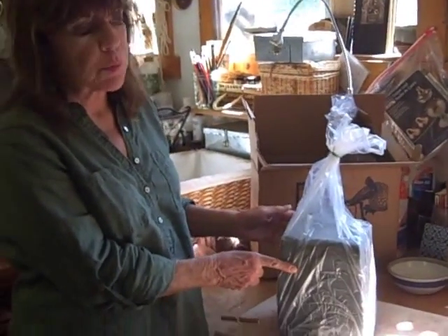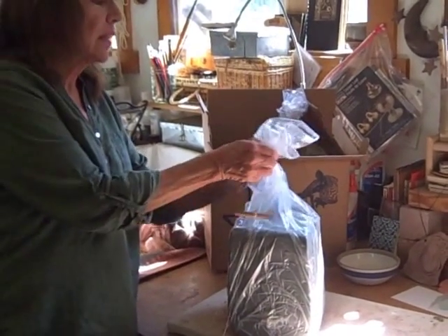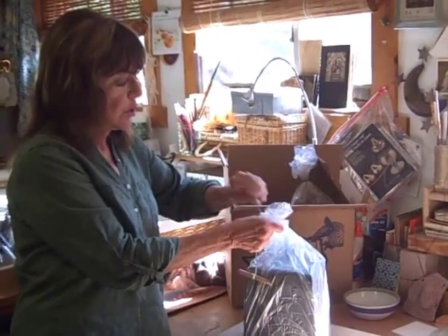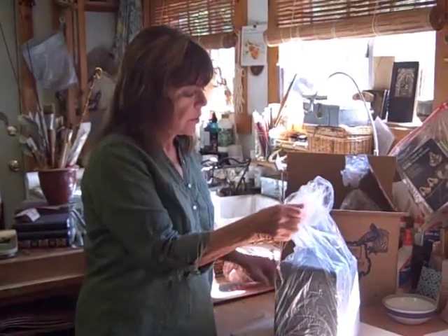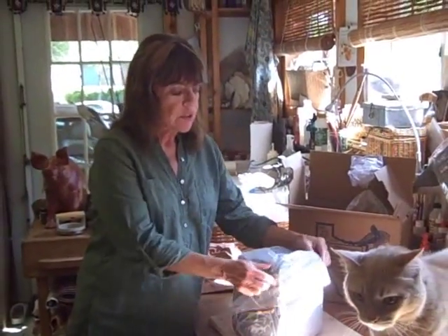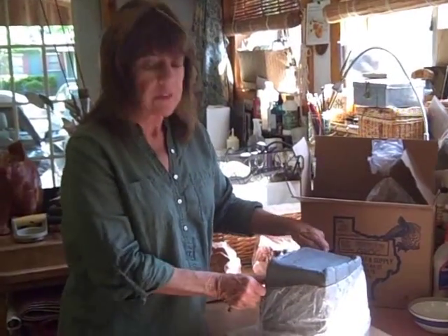First, we start with a clay body for the mold, because we have to have something to do the press mold on. This is a Longhorn white clay, a 25-pound bag. It fires to cone 05, which is an earthenware fire, and this is only going to be the mold part. When we are doing a new face from a sculpture garden or an old cemetery, we always use white clay, because it doesn't leave a red residue on the stone that we're making the impression from.